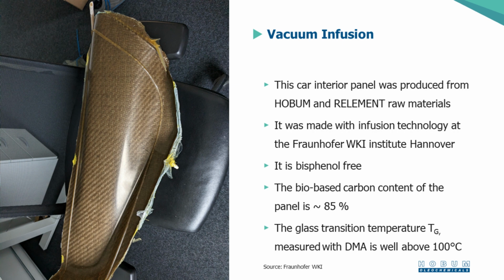Moreover, 3 MPA yields a very good glass transition temperature. This rigid molecule will really boost the glass transition temperature. So this part that you see here on the left was just made in the laboratory at the Fraunhofer Institute in Hanover. And we made it with infusion technology, and we could repeat it several times. It always works. It's a bisphenol-free system. And the bio-based carbon content of this panel, which is a part of, I think, a Renault car, is in the end 85%. And the glass transition temperature is well above 100 degrees, measured with dynamic mechanical analysis.